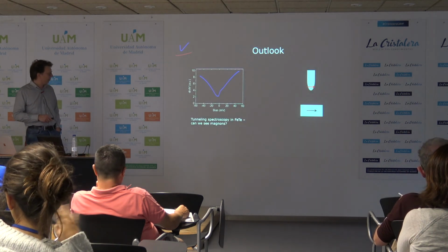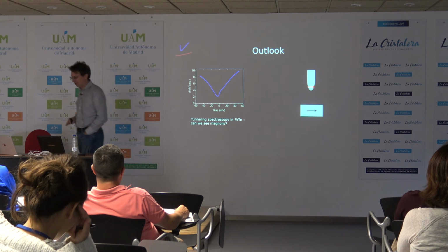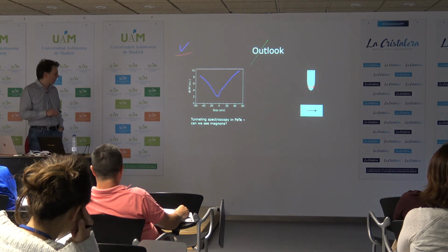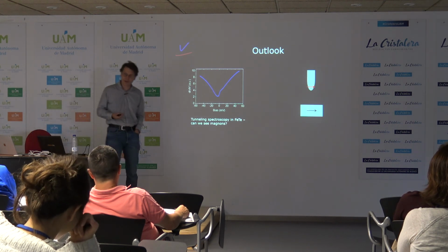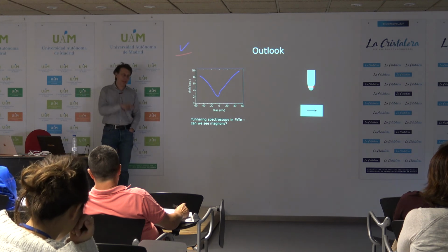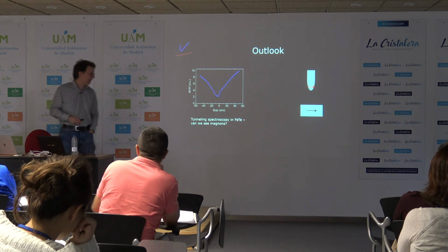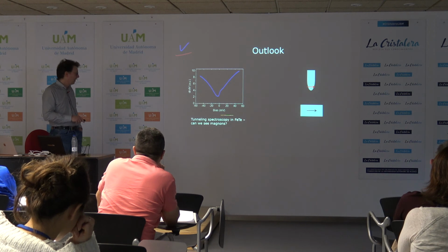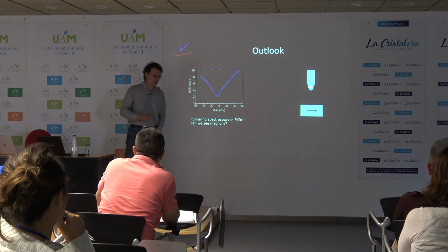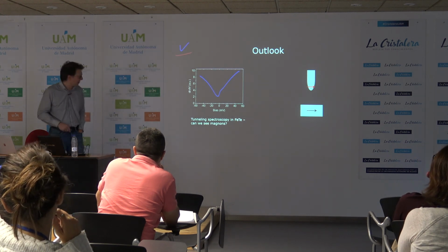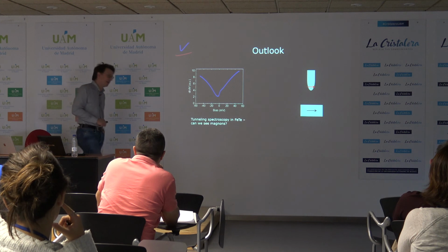And finally, I think one aspect which we've tried to figure out, but I think it's still work in progress, is an important question of whether we actually see also inelastic excitations of magnons in these materials. So in the pnictide superconductors, I think there is evidence that one sees signatures of the spin resonance in inelastic tunneling. But the question is, in these materials where you don't have a sharp resonance, are these spectra actually potentially strongly influenced by magnon excitations? And I think the fact that you get this V-shaped gap seems to be an indication that that's indeed true.